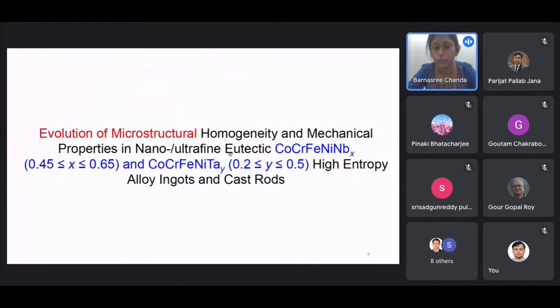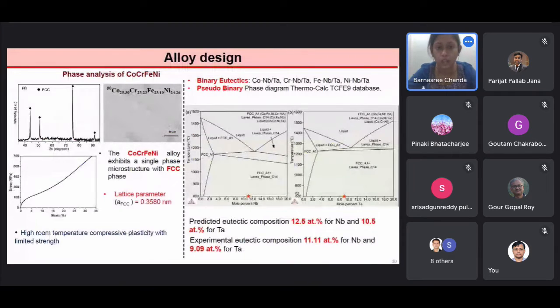Chapter 1: Evolution of microstructural homogeneity and mechanical properties in eutectic high entropy alloy design. So we consider cobalt chromium iron nickel as component A, and cobalt chromium iron nickel has a single FCC phase. From the literature, it has been observed that cobalt chromium iron nickel with niobium and tantalum individually forms a binary eutectic. Therefore, we have considered niobium and tantalum as component B.